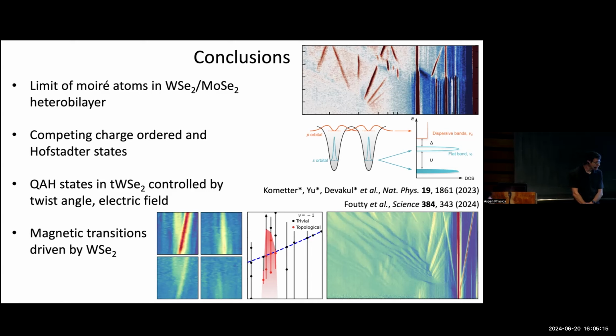I think my high level picture is the following. For these transition metal dichalcogenide systems, the Moiré wavelength is dictated by twist angle, and there's U and the T, and also there's some nearest neighbor repulsion V, again, because Coulomb interaction is long range. So that too may affect things. But as you're changing twist angle, you're changing Moiré wavelength, you're changing the relative values of these. So by doing these kinds of angle dependent measurements, we're actually asking the question, for this physical realization, how does the underlying ground state depend on the parameters of that extended Hubbard model that we're pursuing now?